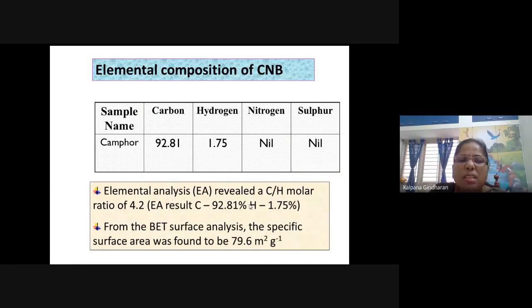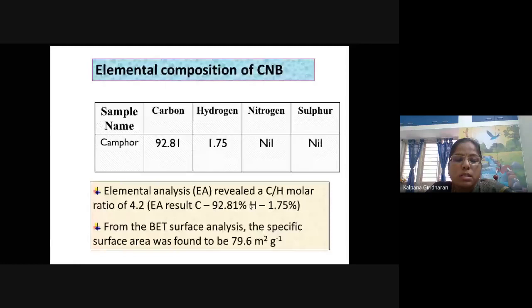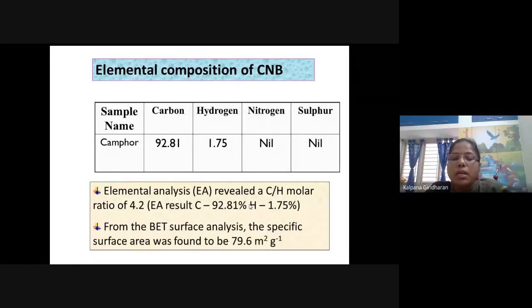This camphor has a high carbon content of 92.81 percentage elemental composition, and the carbon-hydrogen molar ratio is around 4.2. The BET surface area analysis shows around 80 meters square per gram. But even then, since it has good network connectivity, this carbon nano beads from camphor has given maximum capacitance.